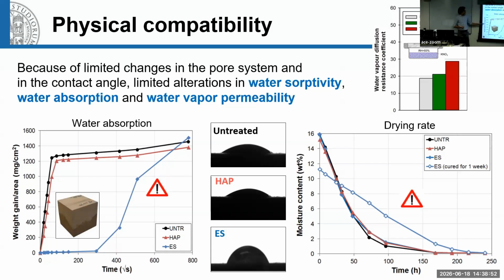However, you see here the amount of water that penetrates into a certain sample as a function of time. In the case of an untreated stone, treated with HAP, it's almost the same, so it's fine. Here you see a totally different curve for the most common commercial alternative, which is called ethyl silicate. I don't know if you have ever heard of this, it's used also in the case of concrete. The particularity about this treatment is that it makes the surface hydrophobic for a certain time.